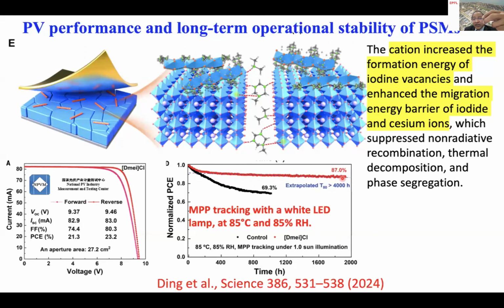So this way you increase the stability of these perovskite materials as shown here. You can retain 87% of the efficiency, T80, after 4,000 hours of stability. And we also measured at 85 degrees temperature, 85% humidity. And these are the criteria for perovskite solar cells. This work appeared last year, November, in Science 2024. So the efficiency is shown here. 23.2% is the highest for this type of mini module.